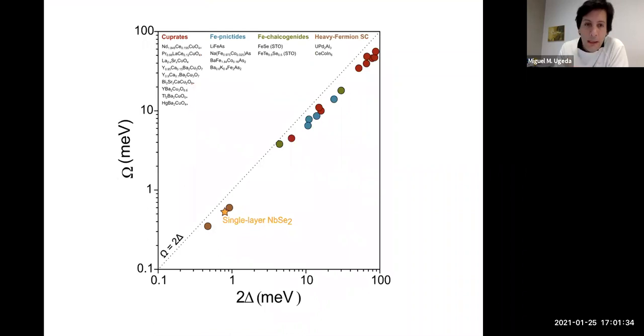And actually, if we plot the value of the fundamental mode, of the intrinsic mode measured previously, against two times the superconducting gap, they all follow this universal relationship below this borderline. And we can locate the case of single layer NbSe2 right here. So we strongly believe that these collective modes are spin excitation modes that originate from the vicinity of magnetism or spin fluctuations in this particular material.